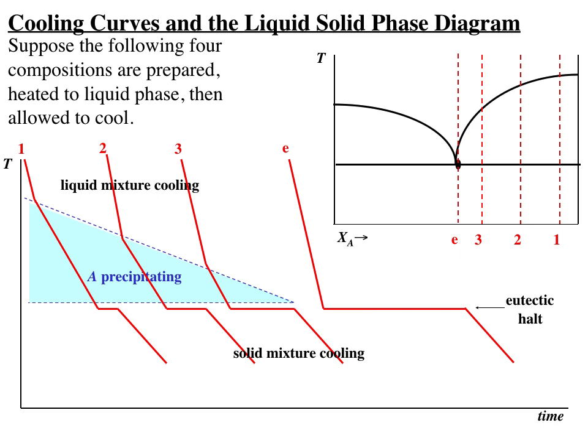What I'm doing there is this is the latent heat of melting point, heat of changing phase, or fusion point, if you like, of the liquid to the solid. This is the temperature of fusion of the eutectic mixture, and I have no change in temperature while that's occurring because it's an exothermic process of heat being released as the materials change from liquid to solid, so there's no ability for the temperature to fall at that point. We call that the eutectic halt. The eutectic composition has the largest time of the so-called eutectic halt.